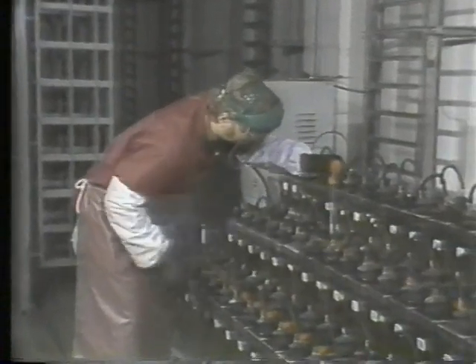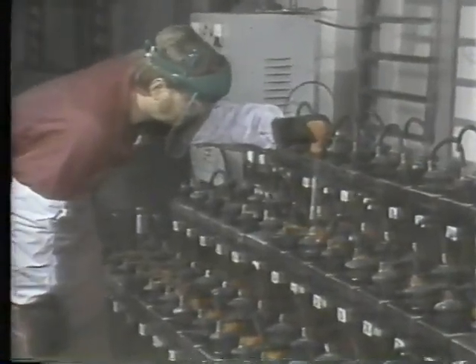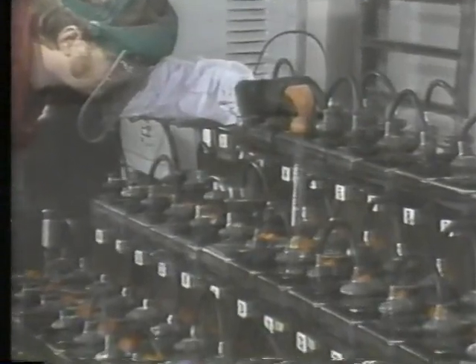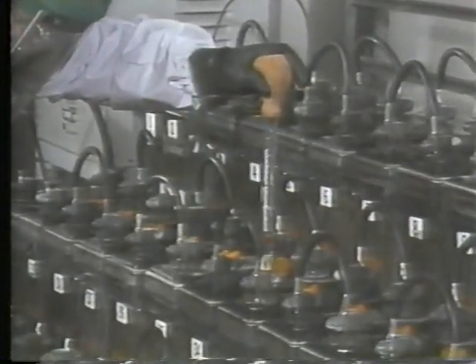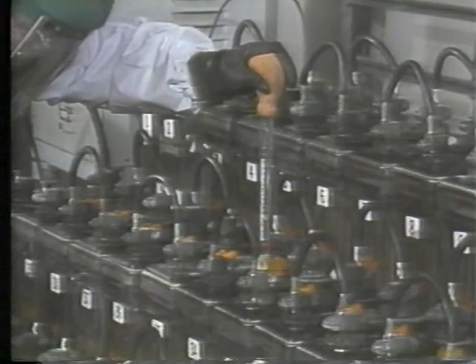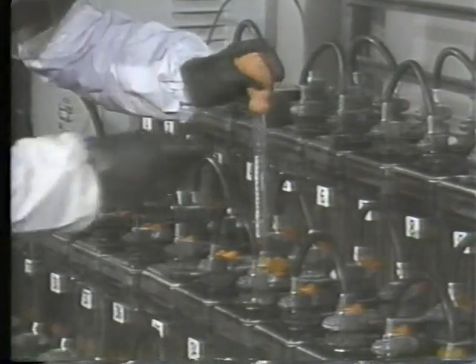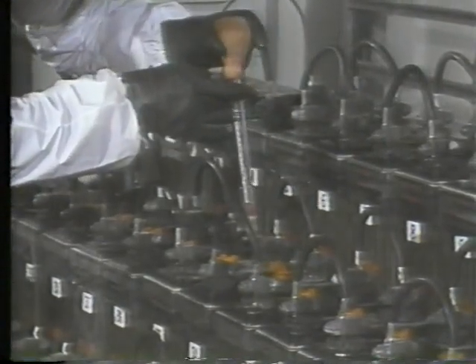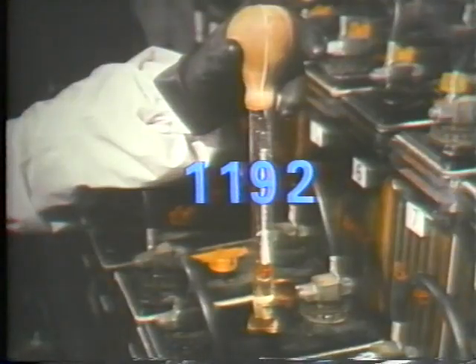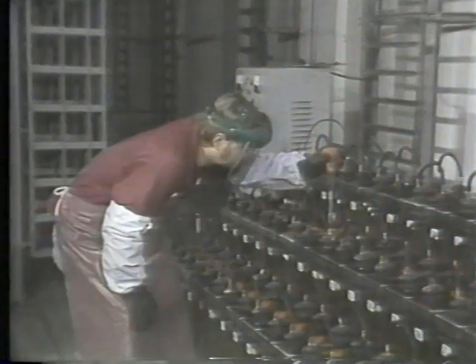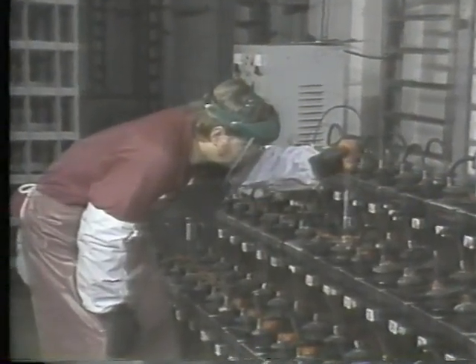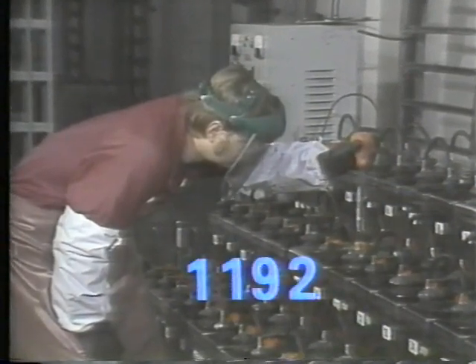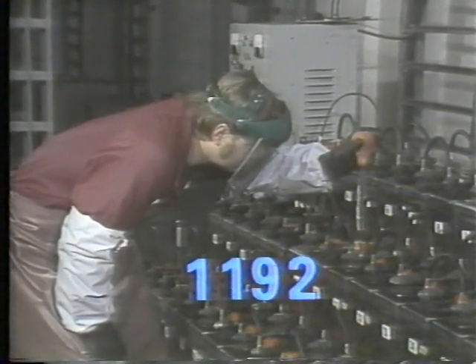Although a routine equalizing charge is sometimes set with a timer for a specific number of hours, the duration of this corrective charge will be determined by hydrometer checks of the lowest cell. Readings are taken every 15 minutes, and the equalizing charge is continued until the specific gravity of the lowest cell remains constant over 5 consecutive checks. Finally, the specific gravity of cell number 34 has stabilized, but it's still below the acceptable range.